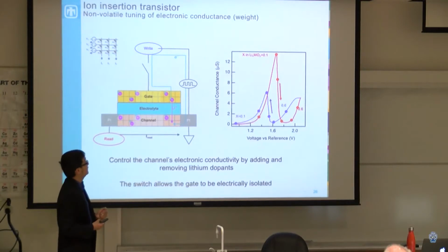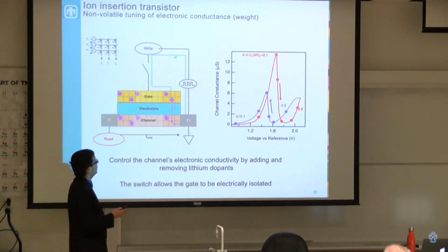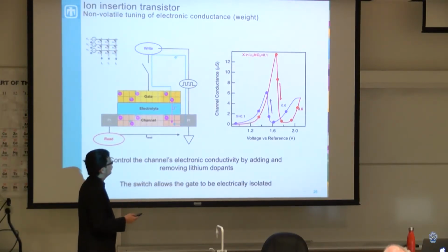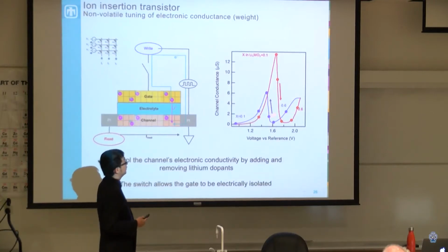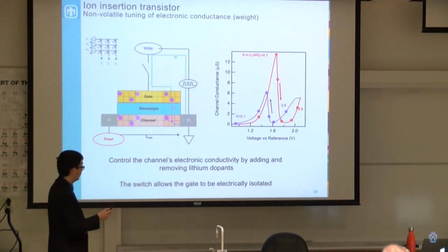And the way this works is that as a function of voltage, we apply voltage to charge this material, so that we can change the electronic conductivity. If we increase the lithium concentration, we can move more lithium into this material and then change the conductivity, and it's reversible on the way back.